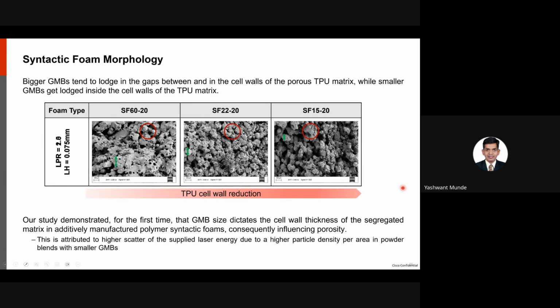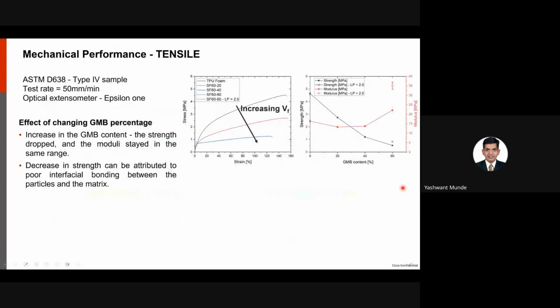So we wanted to see how these manifest as mechanical properties. First, in tension. As expected, as we increase the volume fraction for a fixed particle size, the strength dropped and the moduli stayed in the same region as shown here.